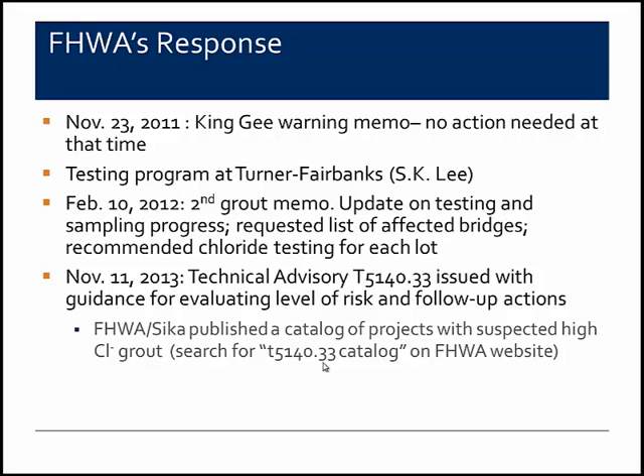And then in February, a few months later of 2012, they issued a second grout memo. This provided an update on the testing conducted both by Sika and the FHWA and the sampling in progress. They then requested from the states a list of suspected affected bridges that may have used that SikaGrout product. And then they did recommend at that time that the states actually perform chloride testing for each lot of grout received. And that was something that had not been done typically to that point.